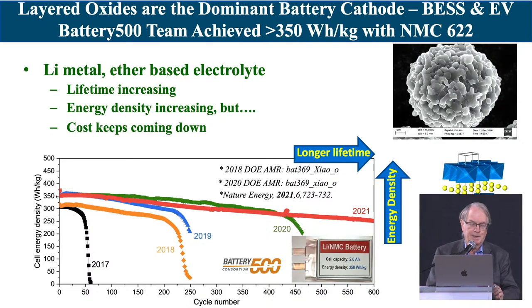I also want to point out the morphology of the particles we use in these batteries is what we call meatballs. So they're comprised of primary particles 100 to 200 nanometers, and these secondary particles are about 10 microns across. And if I mention numbers like 622811, that's just referring to the ratio of the nickel to the manganese to the cobalt.